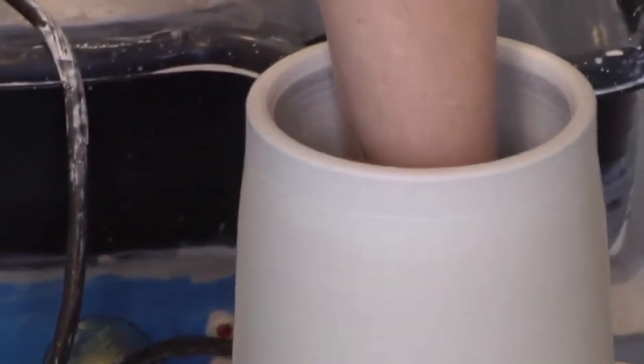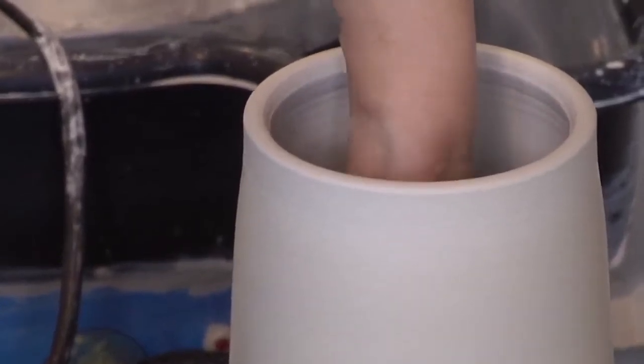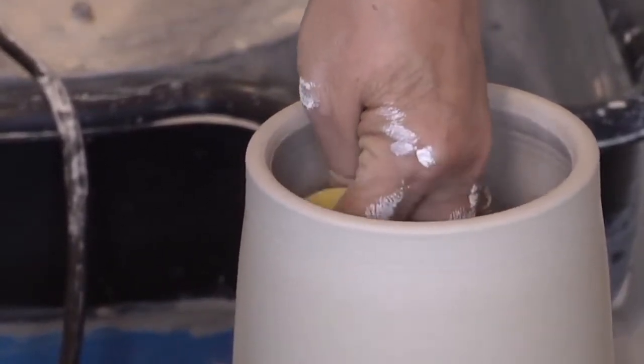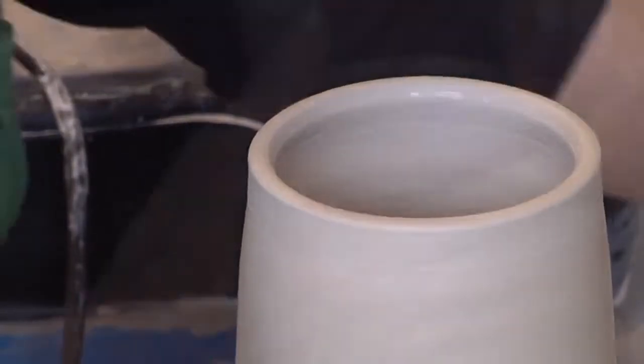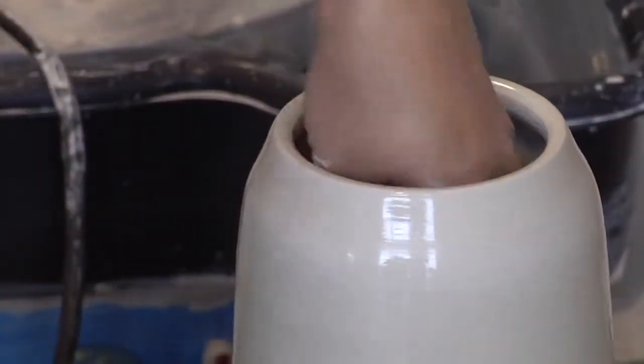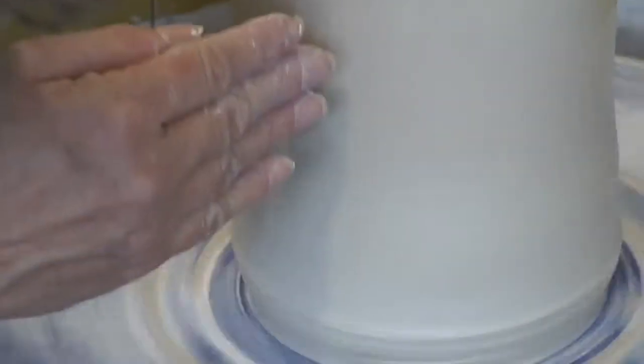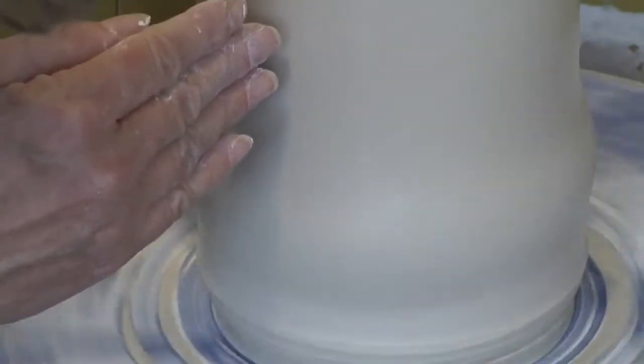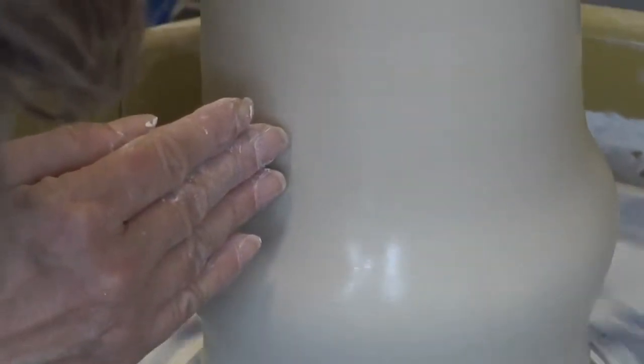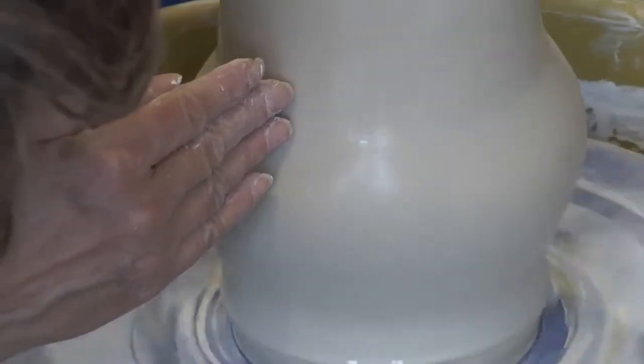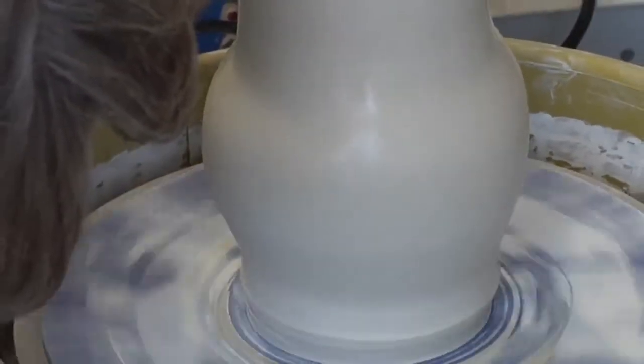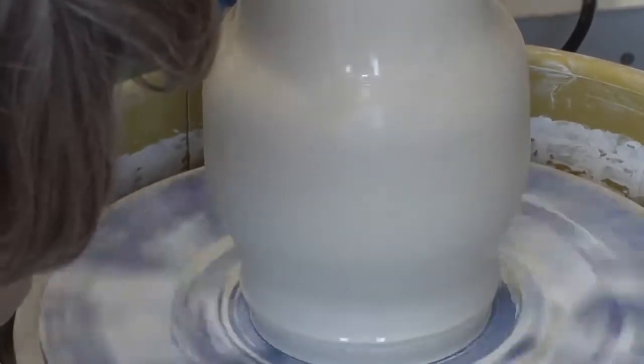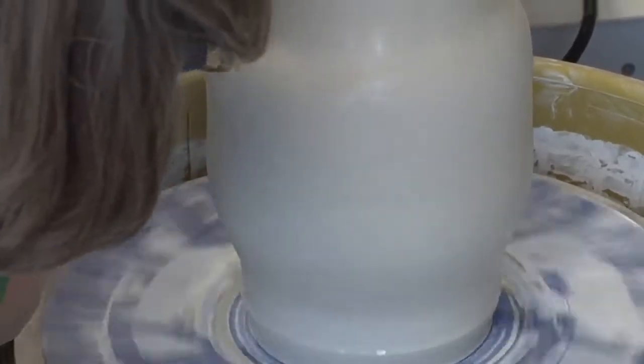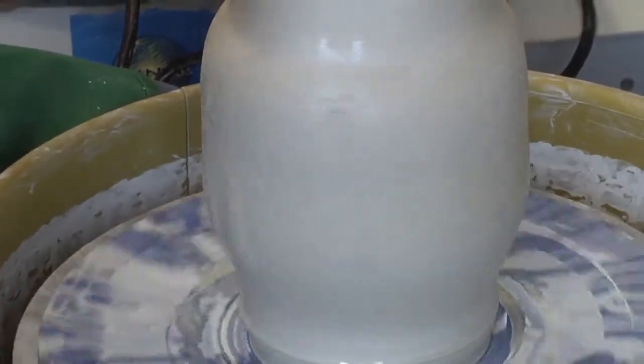I think that'll do. Okay, so I'm going to take a small wooden rib, and first I'll wet the inside. I hope it's not too dry. Okay. The sodium silicate seals on the top surface, and so when it goes to stretch, it cracks. And that's what creates the pattern. It's just the cracking top surface. So you can't touch the outside once you start doing this because you'll mess up the pattern of the crackles.